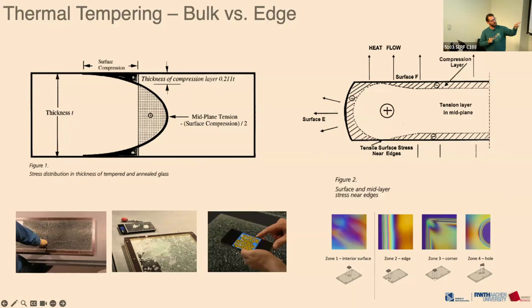It's probably lower here, but it does create an area of lower compression inboard of your edge, which would be scary, and especially more scary when you go thinner, because you have less safety margin. It more than likely exists in thicker tempered glass too, you just have a thicker compression layer it's buried under, so no one really cares that much. As you get thinner, this will become more pronounced, as well as around things like holes, junction boxes, and corner profiles. So it would be a little scary, in terms of how to quantify the stress profile on a thermally tempered perimeter and areas around holes.